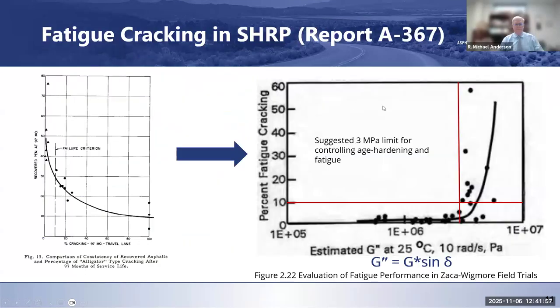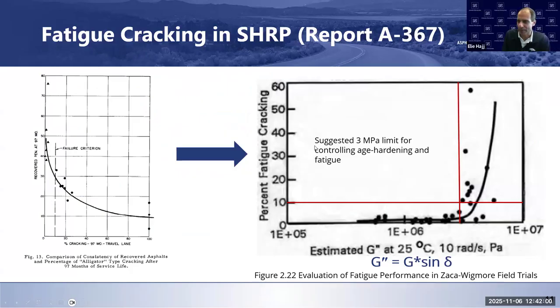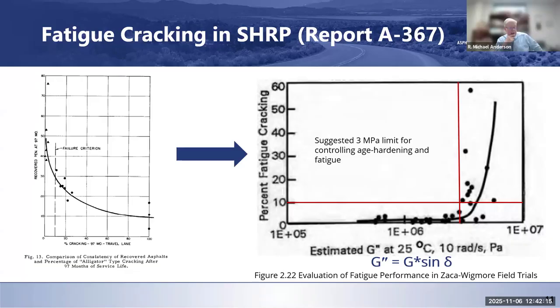The question is, what was the depth within the pavement for the recovered asphalt binder? And does this imply that the specification that was developed based on this information is for near surface binder characteristics? That's a great question. I don't know that, and I'd have to go back through the report to see what the depth is. My guess is they probably took conventional cores out of this roadway and then recovered it, which would have meant they used the entire depth of the layer that they were looking at.